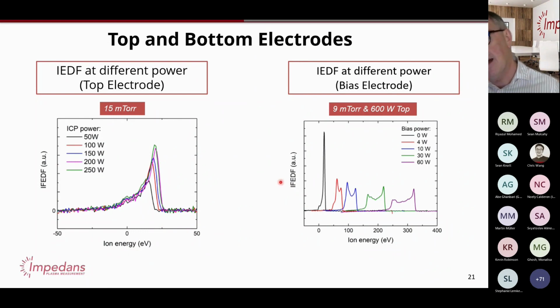Okay, I think I have this one here. So how low energy can an RFEA measure? It actually depends on the voltage supplies. Ultimately, what we call energy is really the voltage applied to the grids. The ones we build use power supplies which are capable of 0.1 volts. So in principle you can get 0.1 eV resolution. That means you can start at 0 and go up in 0.1 steps if you wanted and measure ions at energies that low.